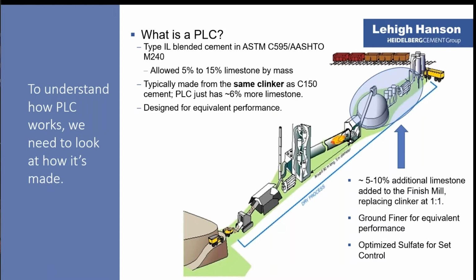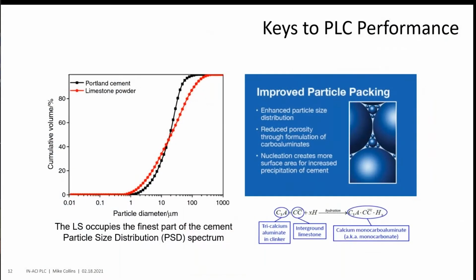And the cement is a part of that. And so the sulfate that the cement brings to the system is really tasked with controlling a lot of the reactions that take place once hydration begins. And so we are able to optimize the sulfate content on our end as a cement producer when we do make that 595 cement.